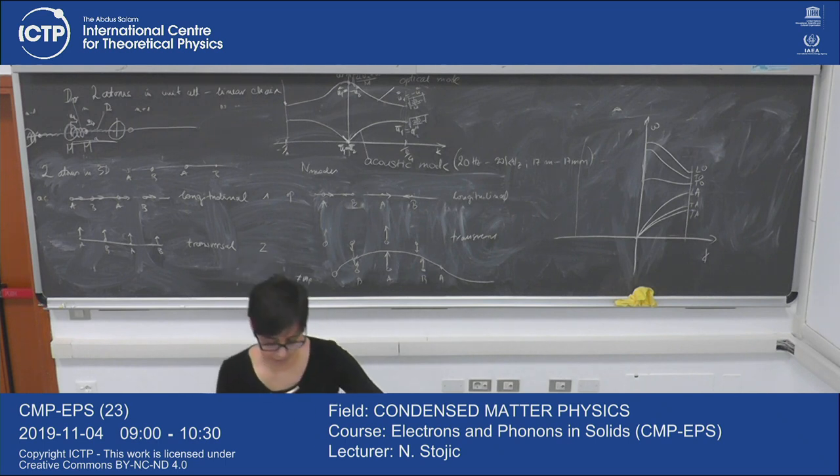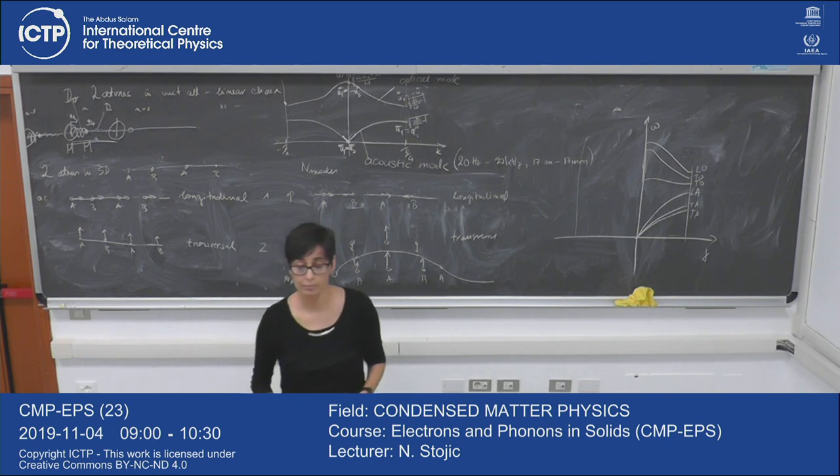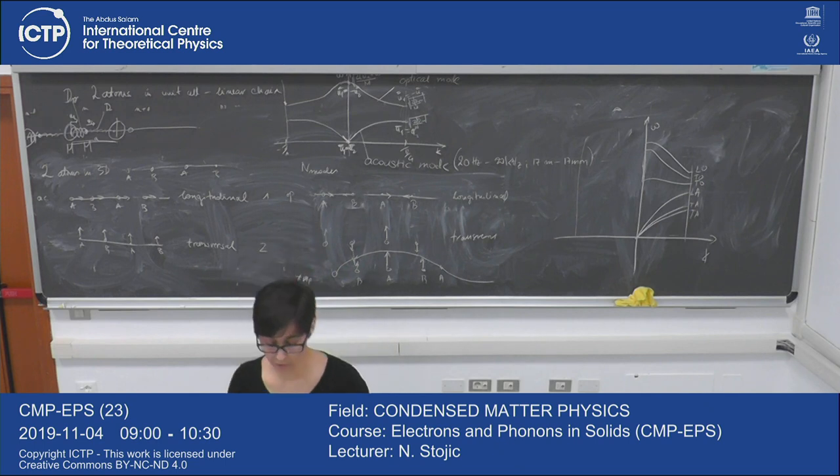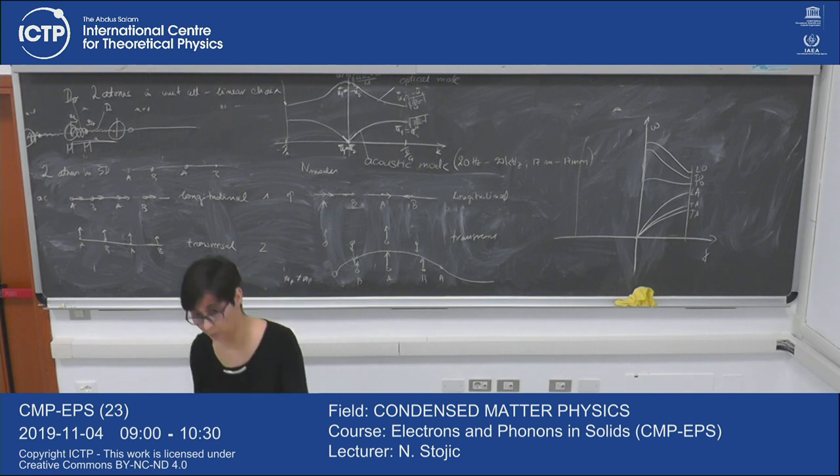It is exactly from, I think, 5D to 6S. Transitions like that are actually absorbing strongly, I think blue light. It absorbs very strongly. It changes the reflectance. Normally, reflectance is very flat for metals. This one has a gap in this part. And this is how you see the shining yellow light. So it is atypical for a metal. It is due to spin orbit. I didn't know this before, actually.